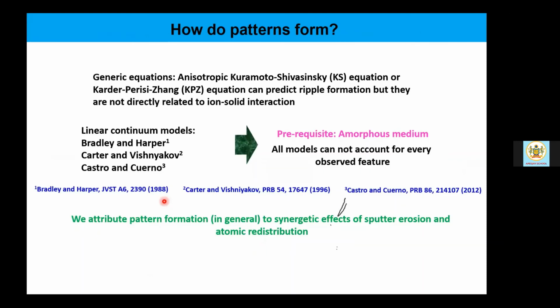Now, mostly generic equations like anisotropic Kuramoto-Sivashinsky equations, these are nonlinear continuum theory-based equations, and some damping terms are introduced. The Kardar-Parisi-Zhang equation can predict ripple formation, but they are not directly related to ion-solid interaction. They are more generic in nature, like sand dunes in the deserts, whatever ripple formations are observed. I mean, they can very well be taken care of by these kinds of equations. So linear continuum models: here, the prerequisite is the surface has to be amorphous in nature. So ion bombardment actually gives rise, under such high fluences, to this kind of amorphous surface, which we schematically demonstrated earlier.